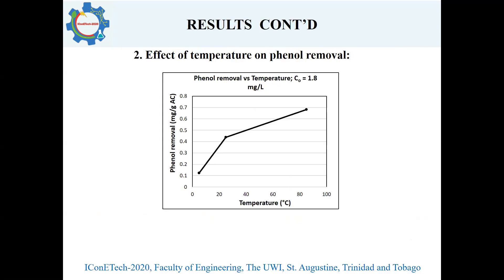I studied the adsorption at different temperatures and found that as temperature increased, the amount of phenol removed by the activated carbon increased as well. This could be due to chemisorption taking place, which is usually postulated by two theories: phenol-phenol interactions and esterification reactions taking place between the OH group of the phenol molecule and the surface acidic groups on the activated carbon. However, this theory could only be validated by further kinetic and thermodynamic analysis.